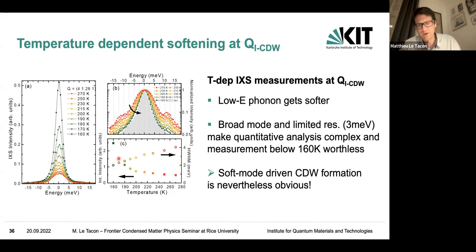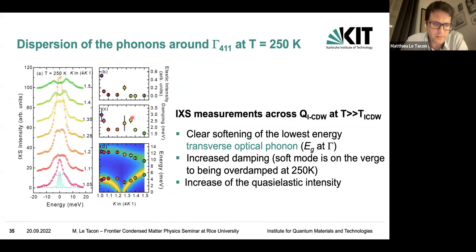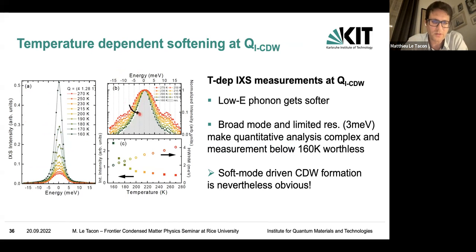So it's really hard with that resolution to come up with a quantitative analysis, mostly because the phonons, as we fit already at room temperature, 250K, are already broad. You do have a low energy feature at around 4 meV, which has a damping of about 2 meV, and it is on top of that with a resolution of 3 meV. So it's very hard to get quantitative as you get closer to the transition temperature. But it's quite clear that there is a soft mode which is associated with the CDW formation.